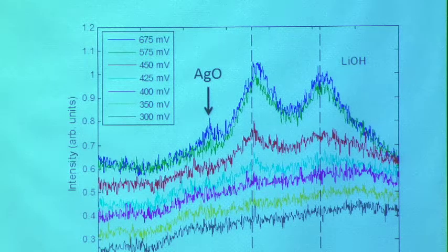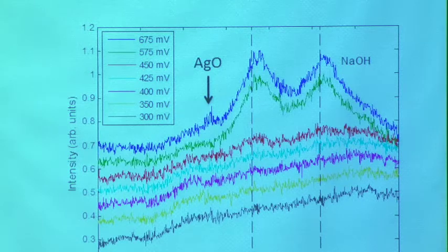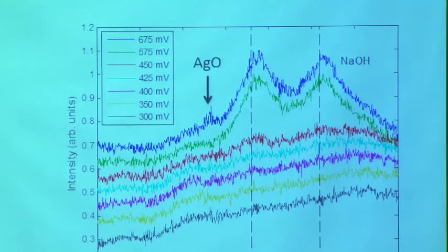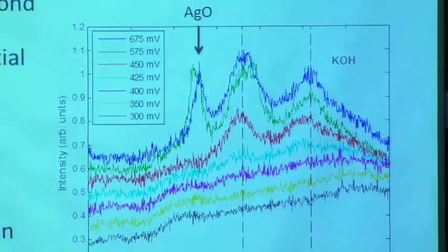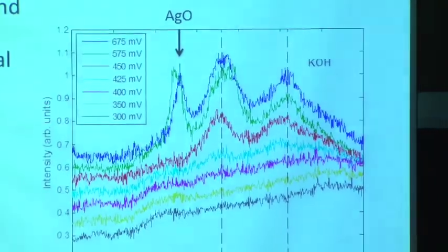Right? If I go now to sodium, it qualitatively looks fairly similar. At low overpotentials where no oxygen evolution occurs, we see no formation of the phase, and you have to go fairly high, somewhere between here and here, before you see the onset of this phase forming. Right? And also very little silver oxide. So sodium hydroxide was second most active, it was above lithium. Lithium, then sodium.